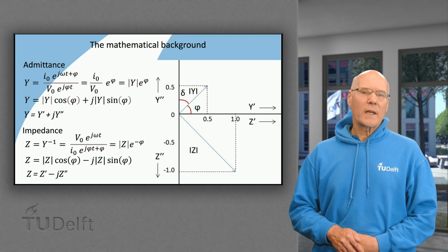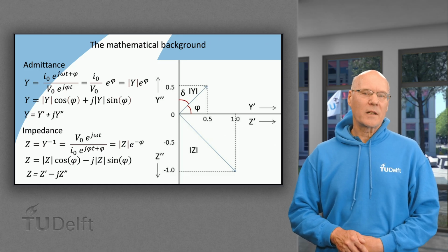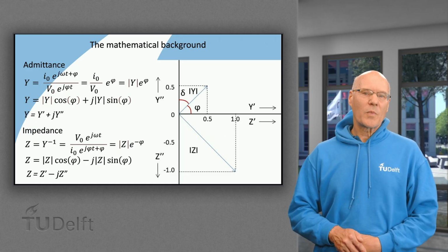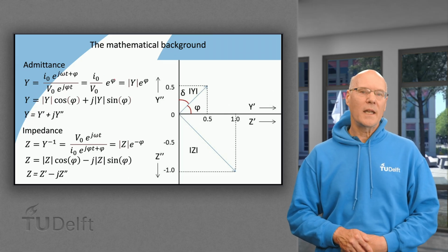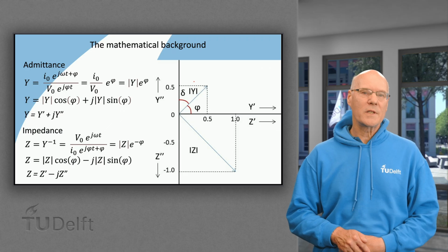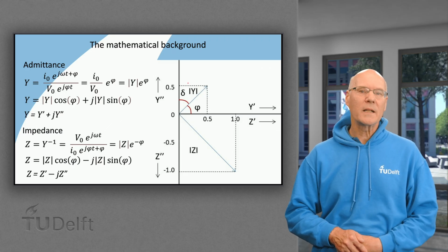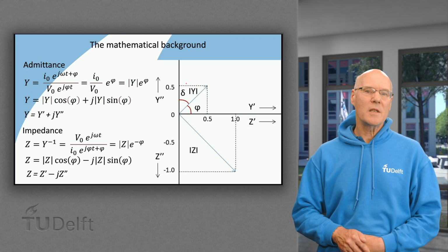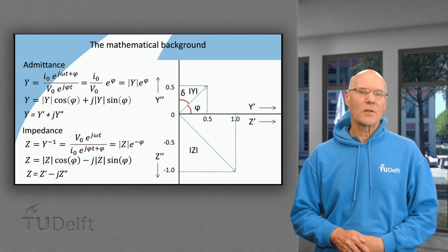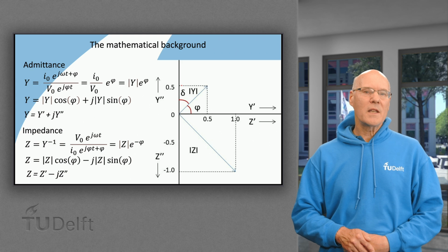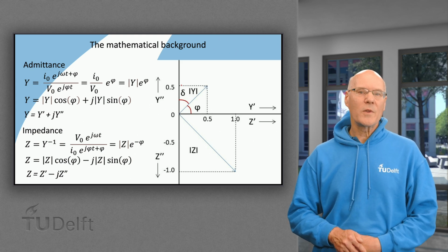In all, it looks quite complicated, mathematically seen. Here we look at the spectrum measured on a circuit where a resistor Rs in series with a system of a resistor Rp in parallel with a capacitor Cp. This last system is usually called an RC circuit. The spectrum then is a semicircle shifted from the origin.